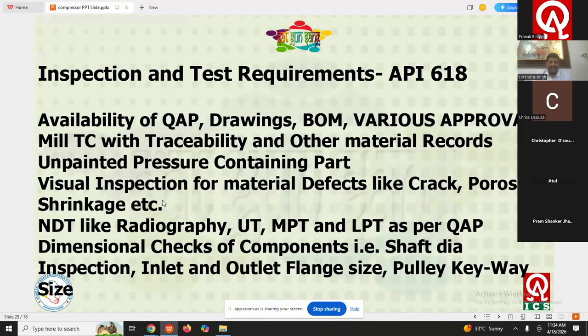Again, visual inspection. So after that certificate and the TC review, the inspector will see the visual inspection, visual defects for the casting for crack, porosity, shrinkage. Then he will carry out the NDT as per the approved QAP, that is radiography if applicable, UT if applicable, MPT if applicable, and LPT if applicable.